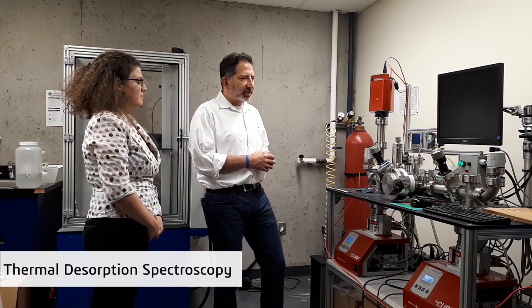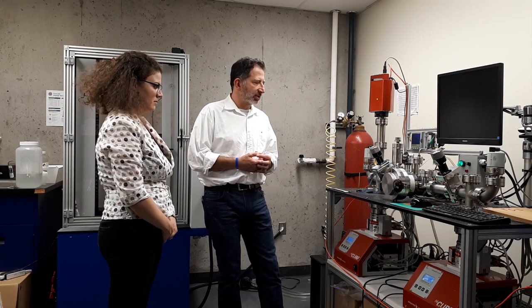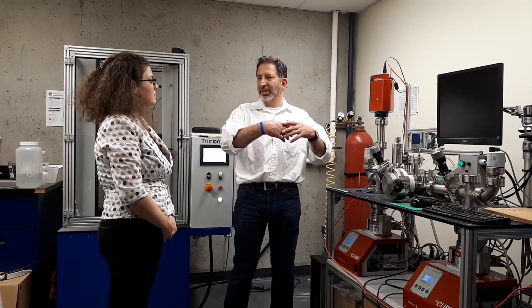The principle of the machine is that we heat it up in a very high vacuum to be able to extract hydrogen from the material, and then we measure the hydrogen. In fact, we extract other things as well, but we isolate the hydrogen. So it tells us how much hydrogen is residing inside the material, and what the state of the hydrogen is. For example, is it in a trap site? Is it in a diffusible state? The amount of temperature it takes to get it to move tells us where it's sitting in the material.